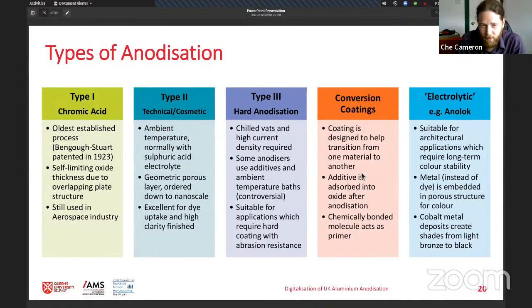It's a very, very hard coating, and it's still used in the aerospace industry today. Type 2, technical or cosmetic anodization, is the type you're probably most familiar with. This is performed at ambient temperatures and using a sulfuric acid electrolyte, which is dissolving the oxide as it forms.